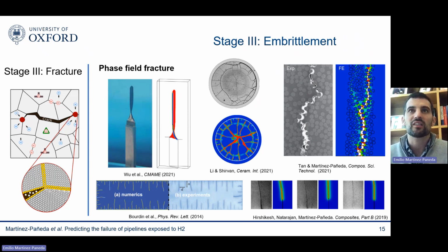And this slide summarizes why these models have been so popular. These are all the outcome of simulations, some from our group, some from other groups. And you can see that over a wide range of materials, here we're dealing with metals, ceramics, composites, even functionally graded materials, we can predict very nicely the output of experiments. And these are the outputs of very complicated experiments. So you can see that not only can we capture very complicated cracking phenomena, crack branching, nucleation of secondary cracks, coalescence of multiple cracks, but we can also do so showing a remarkable agreement with experiments.